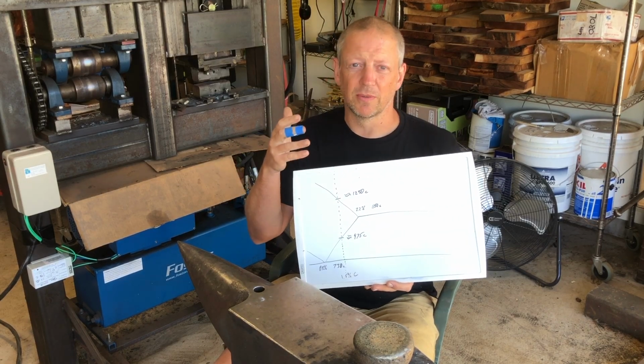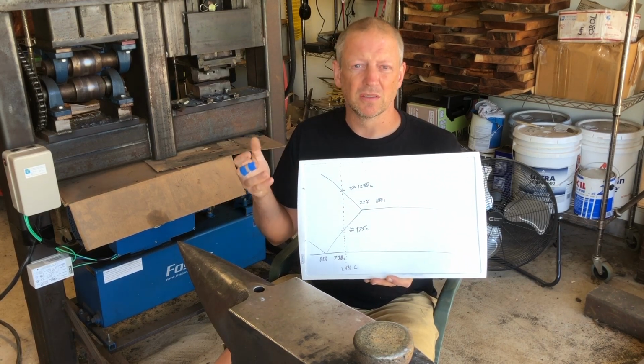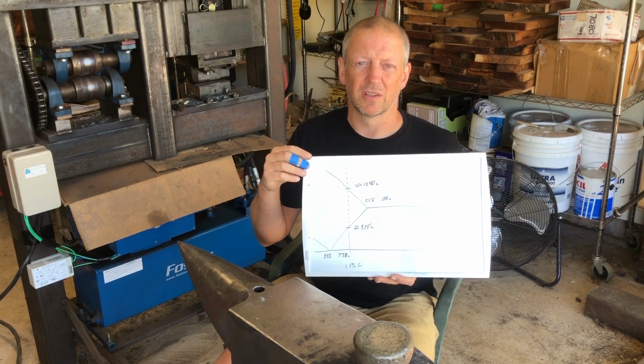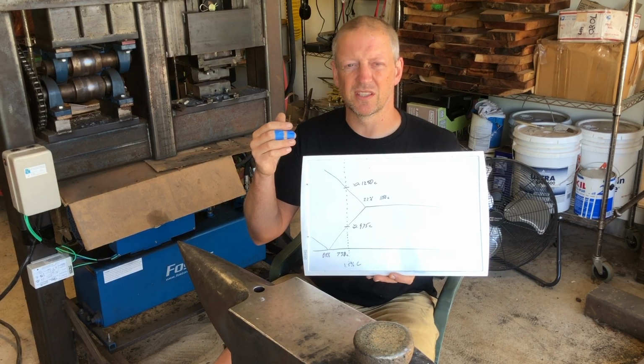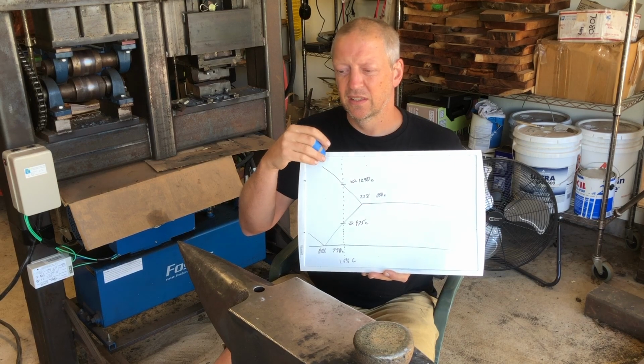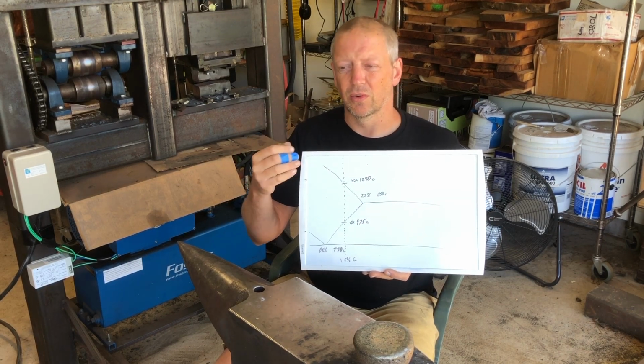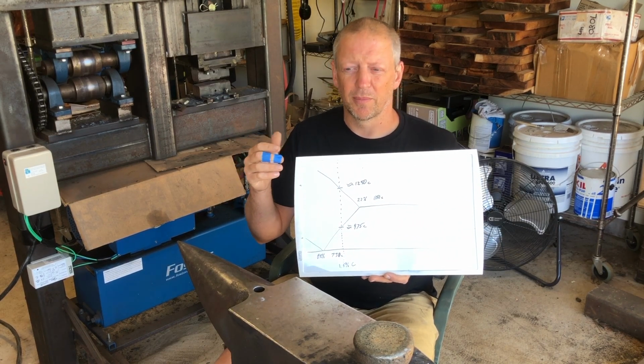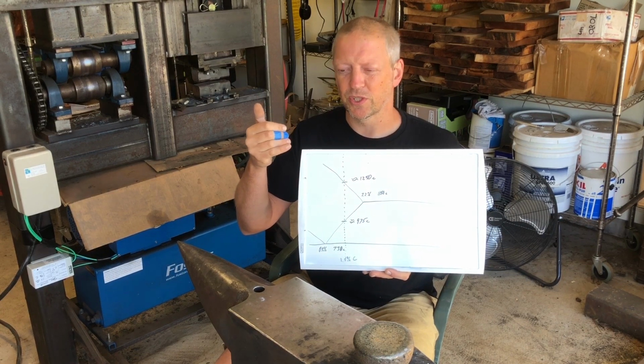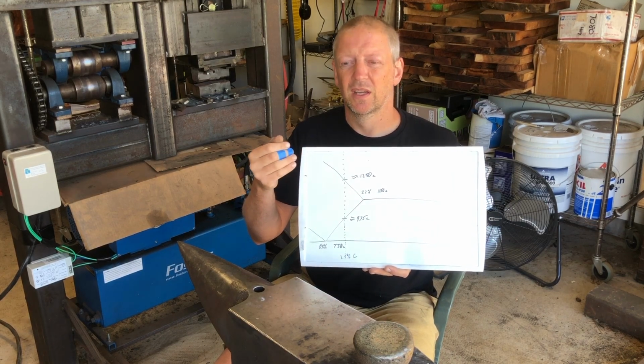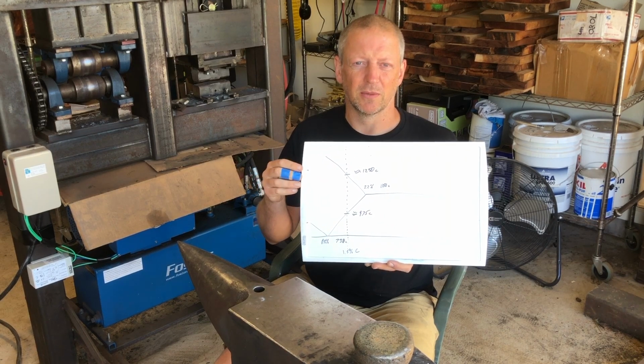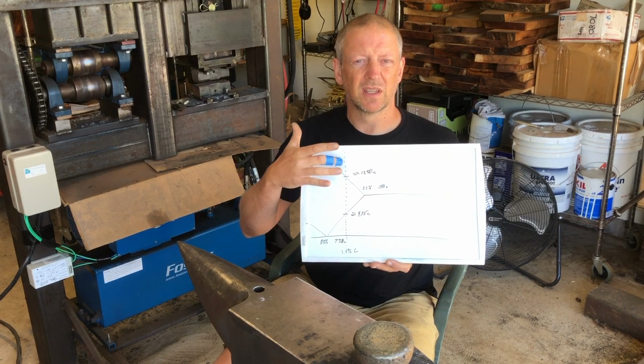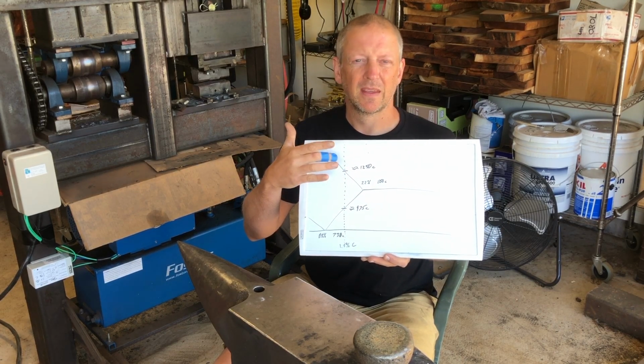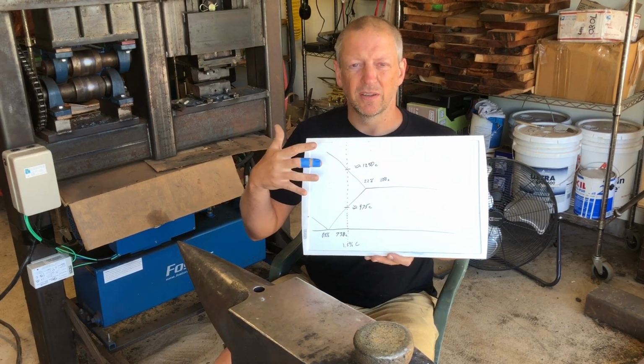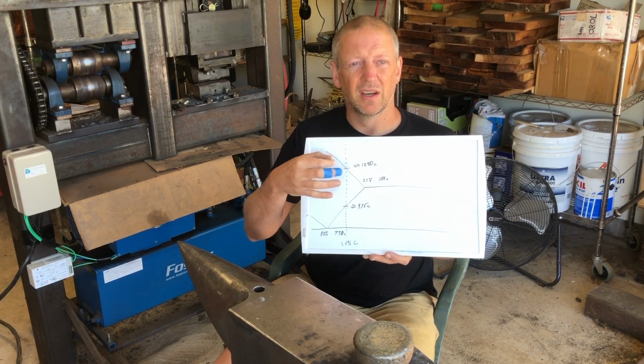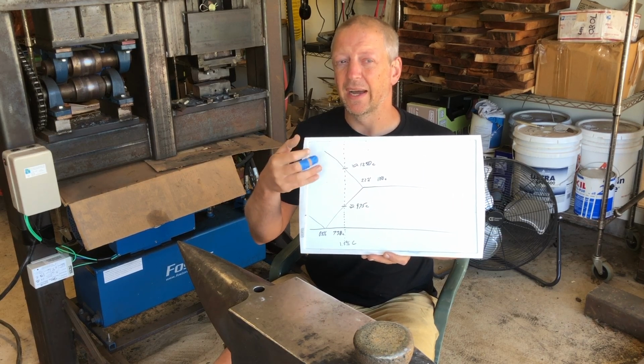Now, in wootz steel and also in most steels, some of those elements are very strong carbide-forming elements. So things like vanadium, very strong carbide-forming element, also sometimes referred to just as CFEs. But you can also have slightly weaker ones like tungsten or chromium or molybdenum. They're still strong carbide formers, but they may not form carbides at quite as high a temperature. But they are being concentrated between the dendrites, and carbon is also being concentrated between the dendrites. So as we're cooling here, and then finally reach full solidification, the structure we're going to have is the pure iron dendrites with these pockets of much higher carbon and higher CFE concentration.